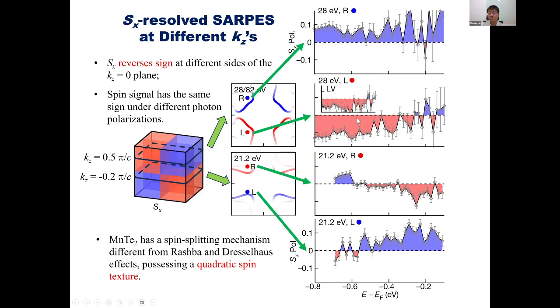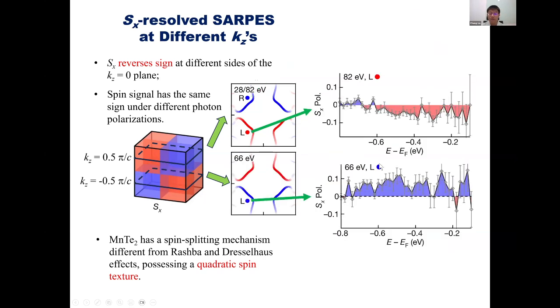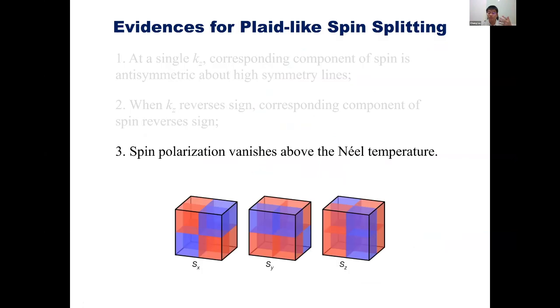And we even changed the polarization of the incoming light to make sure that this is not what's called a final state effect in the ARPES measurements. When we changed to another photon energy, the Kz plus changes to Kz minus, and then the red one changes to blue, and the blue one changes to red. So everything fits quite well. And we actually have more data on another Brillouin zone. At 82 electron volt, this one is red, and at 66 electron volt, this one is blue. So using systematic ARPES measurements, we can make sure that when the Kz changes, the polarization will change sign.